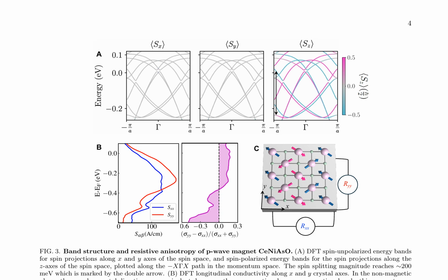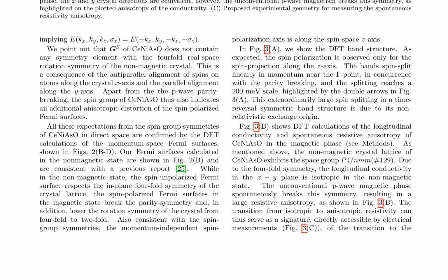The Fermi surfaces calculated in the non-magnetic state respect the in-plane fourfold symmetry of the crystal lattice, whereas the spin-polarized Fermi surfaces in the magnetic state break the parity symmetry and lower the rotation symmetry of the crystal from fourfold to twofold. The momentum-independent spin polarization axis is along the spin space z-axis, consistent with the spin group symmetries. The DFT band structure is presented in Figure 3a, showing spin polarization only for the spin projection along the z-axis.